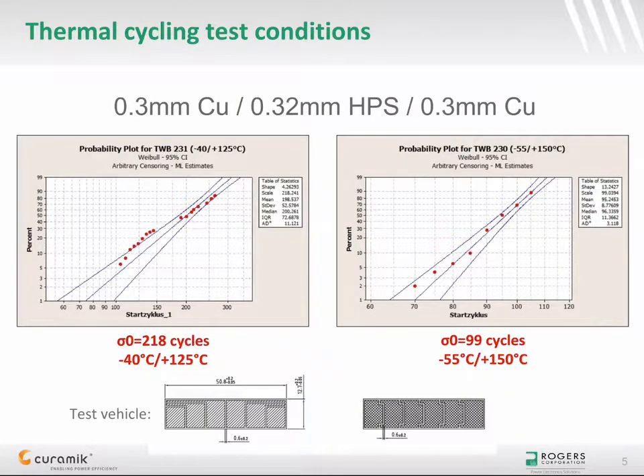As an example, substrate with 0.32 mm thick zirconia toughened alumina ceramic along with 0.3 mm thick copper on both sides have been tested with different min and max temperatures. According to the probability plot, the calculated characteristic life, which is the time at which 63.2% of the units will fail, is 218 cycles when the chosen min and max temperatures are minus 40 degrees C and plus 125 degrees